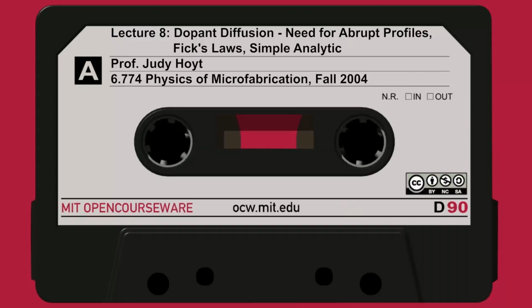So let's go on to slide number 22. Again, F equals minus D partial C by partial x. This is a general flux law, which hopefully may be familiar to you. It's analogous to Fourier's law of heat conduction, or to Ohm's law for current flow. In this case, the proportionality constant is called the diffusivity D. It has units of length squared per time, or centimeter squared per second.